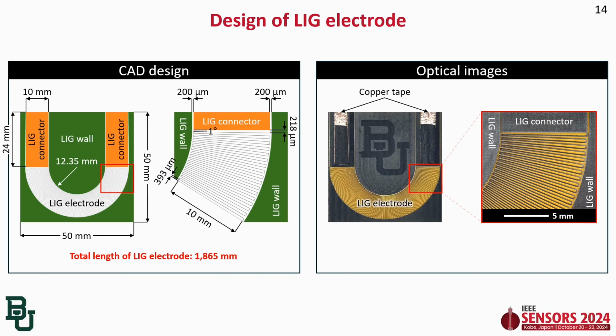The design of the LIG electrode is shown in this slide. To make our surfaces non-wetting to gallium-based liquid metal, the LIG wall is made. We fabricated the LIG connector to connect the LIG electrode with the cathode or anode. The length of each LIG electrode line is 10 mm, and the angle between each LIG line was designed to be 1 degree. We found that gaps larger than 200 micrometers made the surface wettable to oxidized gallium-based liquid metal. Under a gap size of 200 micrometers, there is a high risk of electrical shorting, so the gap between the LIG wall and LIG electrode was designed to be 200 micrometers. The optical images for the LIG electrode, wall, and connector are shown on the right side.